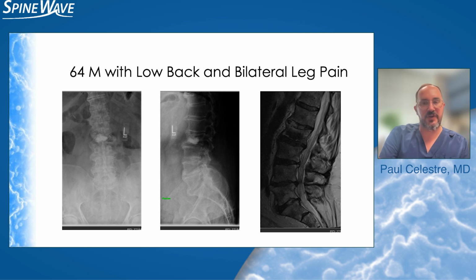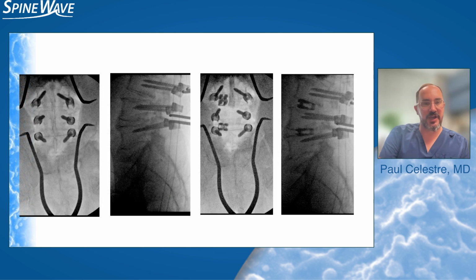His stenosis is largely confined to the L3-4 and L4-5 levels, and I thought he was a good candidate for an L3-5 T-lift using the Exceed cage. I'm a freehand screws first kind of person for people without significant deformity. You can see my initial x-rays on the left, and then my post-cage x-rays on the right. At the L3-4 level, you can see evidence of a hyperlordotic disc even on the preoperative radiographs, and I was able to put a 15-degree lordotic cage there for excellent maintenance and, in fact, improvement of lordosis segmentally. At the L4-5 level, it was a little bit more of a tight disc. This is the 8-degree lordotic cage there.